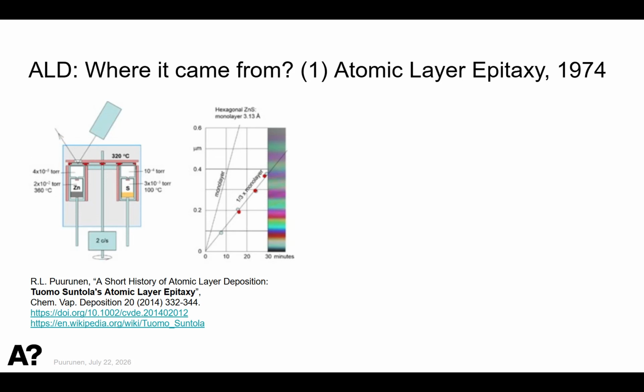They had only 1/3 of a monolayer, and to us, from today's perspective, of course, this looks like an excellent first experiment where you could get the film that you wanted. And Suntola's disappointment also later vanished when he understood why it's not a full monolayer growth, but less. And the reasons for this vary depending on the process.